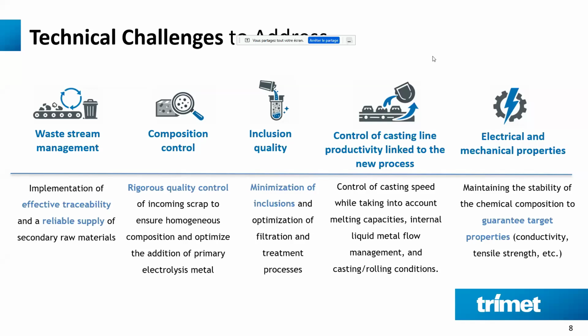Then there is a topic about the inclusion quality. That's where we minimize inclusions and increased our process control. And this also has an impact on our casting possibility, since the furnaces that we use to produce wire rod were only fed with primary aluminium, meaning aluminium coming from the electrolysis at already 900 degrees. Increasing the recycling content has an impact on the furnace capacity to follow the speed of the wire rod mill. And this also has an impact on the different conditions for casting and rolling coming from this recycling content.